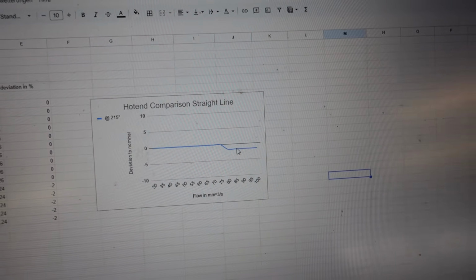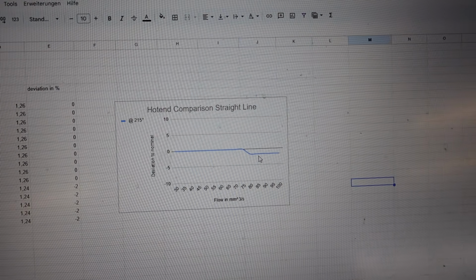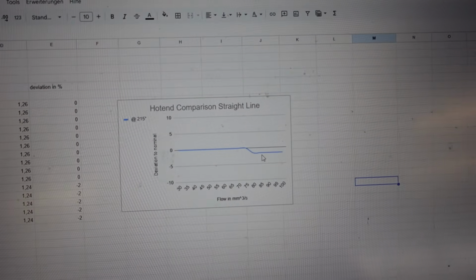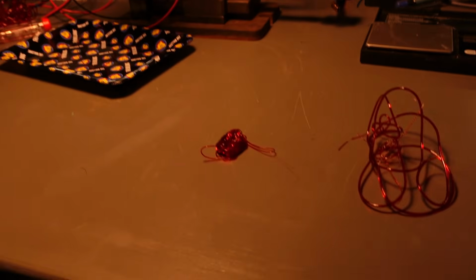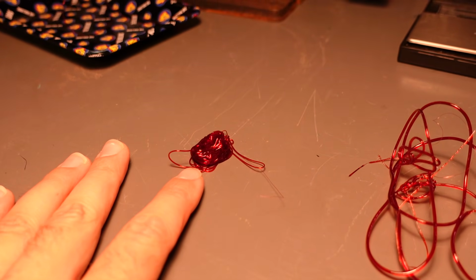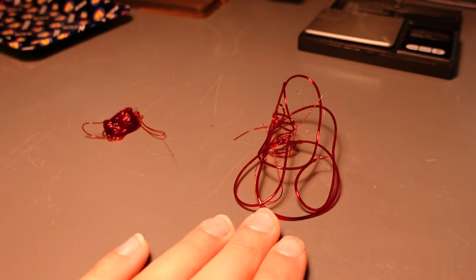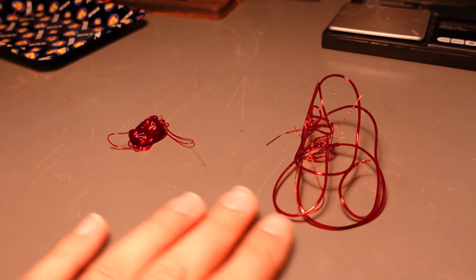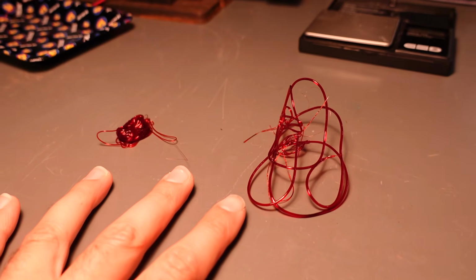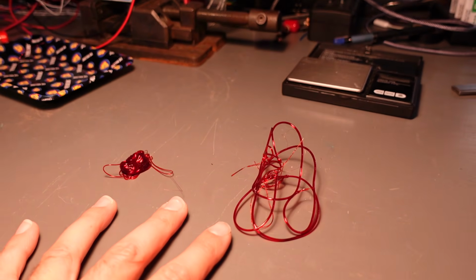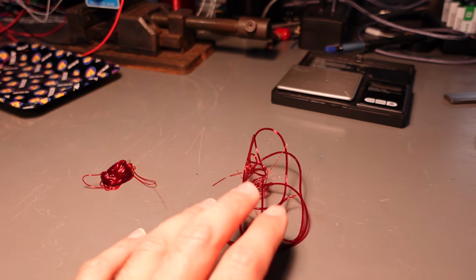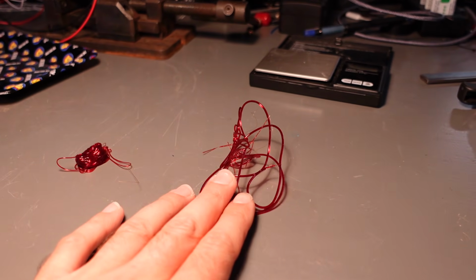I could extrude material all the way to the end. There is just minor deviation to nominal, which could just be from compressing the filament. But have a look at this here. This is what material looks like at 35 cubic millimeters a second, and this is at 100. So this is clearly not the same, even though the scale says they're the same. But in a real world printing application, this material isn't coming out hot enough out of the nozzle.